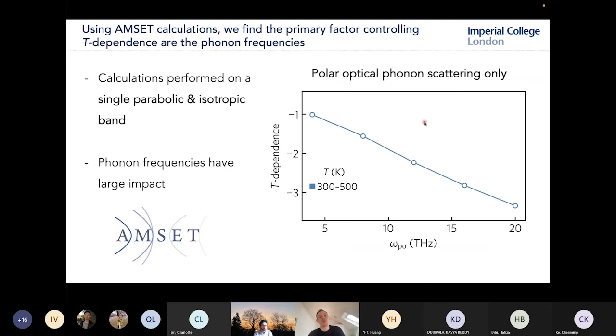So here I'm trying to go back to as simple a picture as possible. So I'm performing AMSET calculations on a single parabolic band, an isotropic band as well. So basically, this is going back to those idealized models. But here I'm using the full scattering rate equations which we have available in AMSET. The other thing I should mention is that I'm only including a single scattering mechanism here, and that's polar optical phonon scattering.